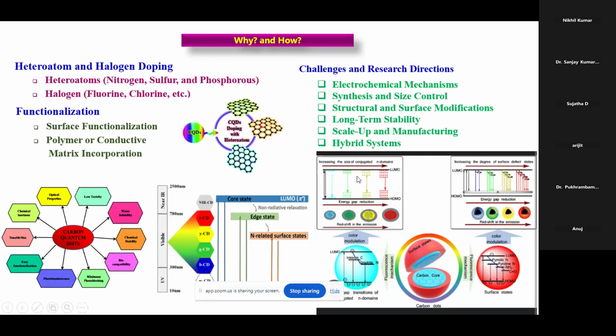Hybrid systems. While increasing the size of the conjugation, the π-domains also change. According to the size, there is a shift in the emission. When size increases, the emission shifts to red, so the energy band gap gets reduced. This is the mechanism. Then increasing the degree of surface states also plays a role. When we dope the system, it gets a defect state, and according to this defect state, the band gap gets reduced.